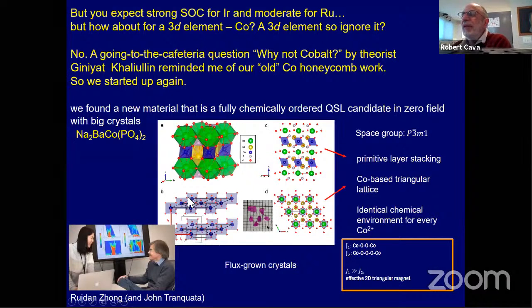I said, can you make some honeycombs out of cobalt? Well, first she worked on ones that we had worked on, and then she started putting things together, and she found that sodium 2 barium cobalt phosphate didn't make a honeycomb, but it made a triangular lattice. So now these blue octahedra, this is a new compound never before discovered, and these blue octahedra contain the cobalt, and when you look down on this plane here, it's a triangular lattice of cobalt. And they are not so close together that they are forced to magnetically order at a high temperature.